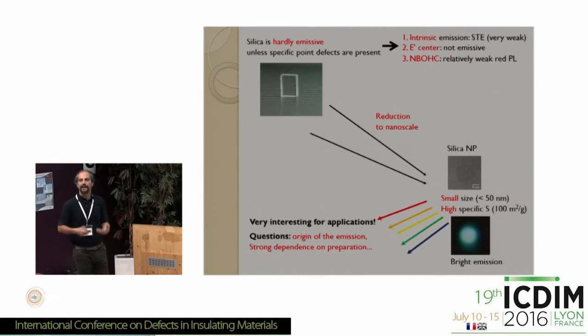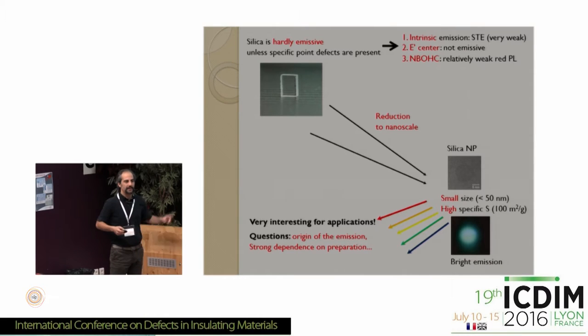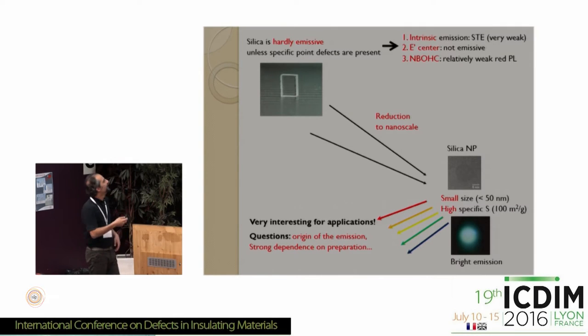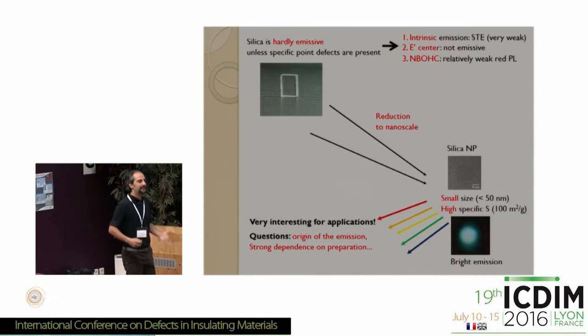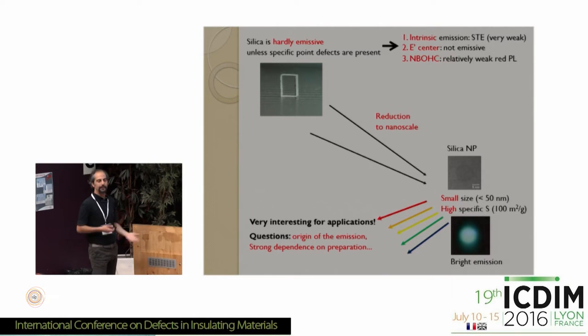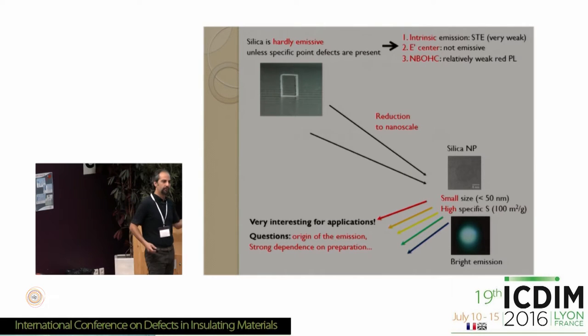Because many studies have seen that silica nanoparticles, here you don't see it very well, I guess, but there is a transmission electron microscopy image of a nanoparticle of silica about 10 nanometers sized. It's hard to see because it's amorphous, but it's there. If you get closer, you will see. Silica nanoparticles, many studies have seen, are very bright emitters. So if you have a nanoparticle of silica, typically below 50 nanometers, this gives rise to very strong photoluminescence emission.